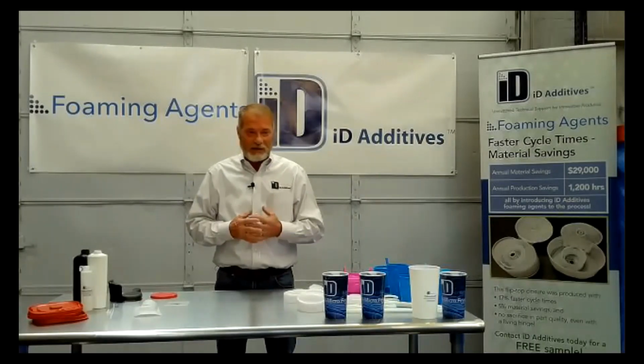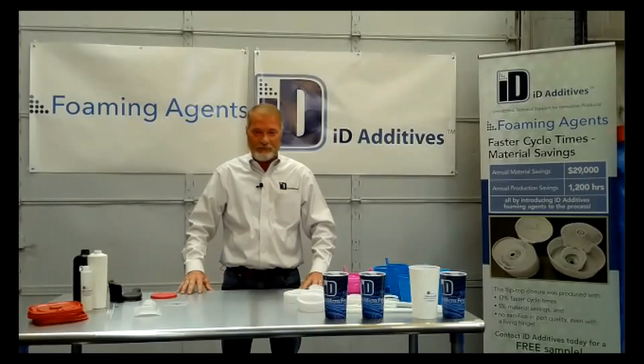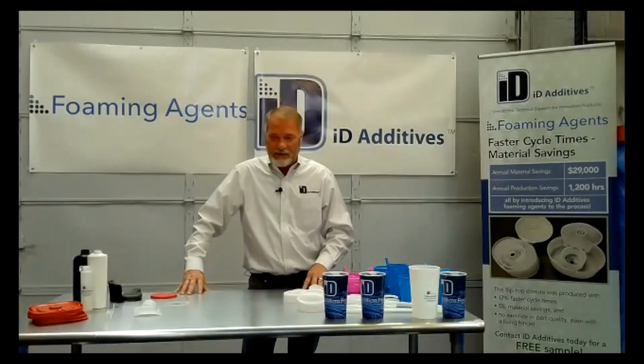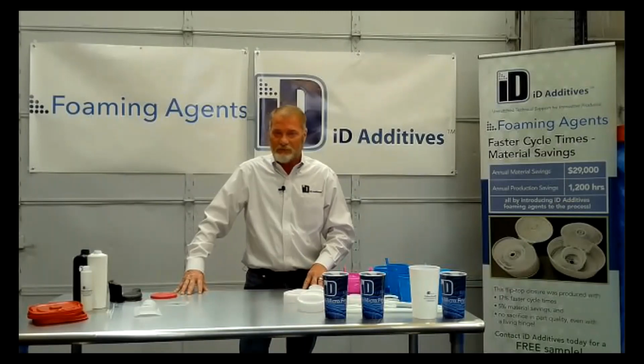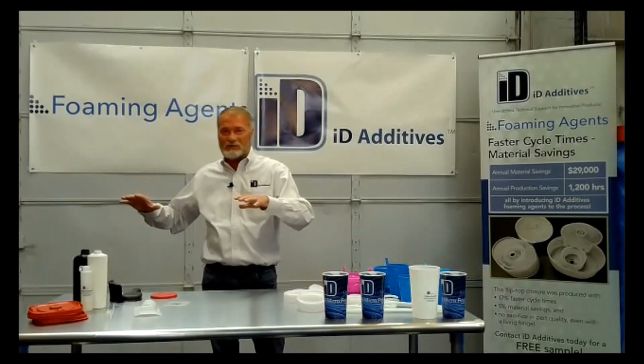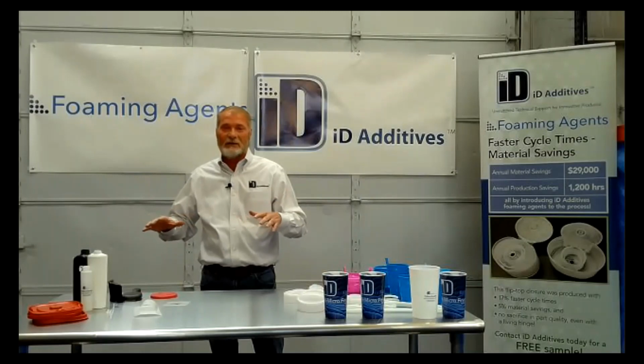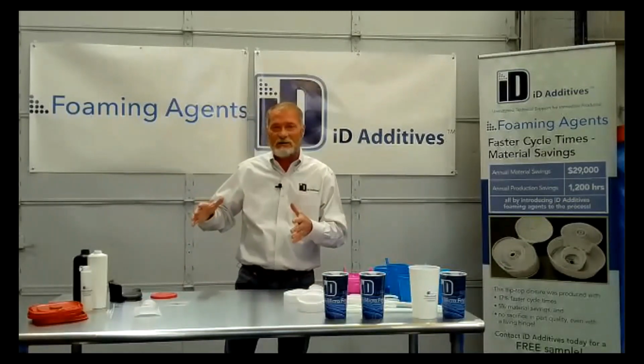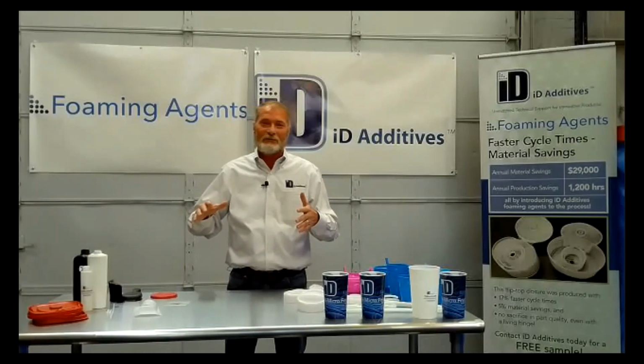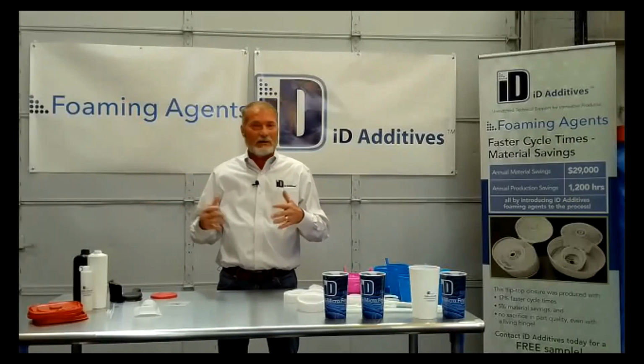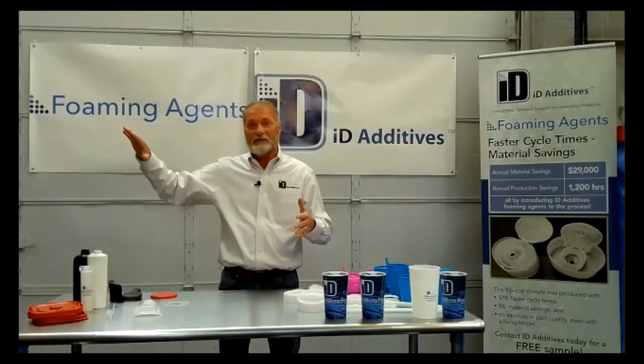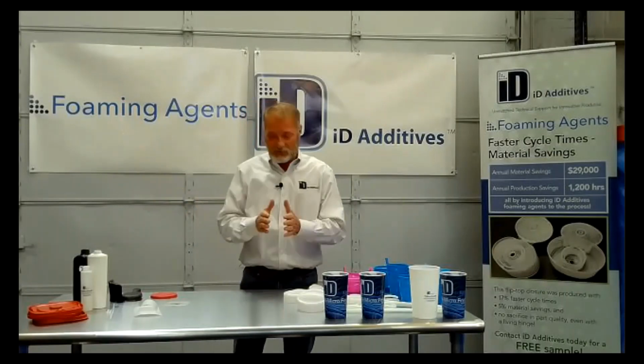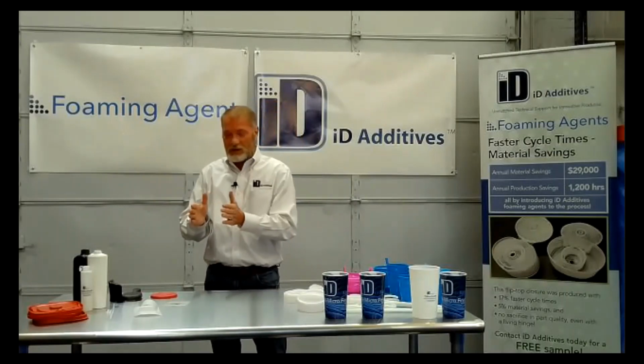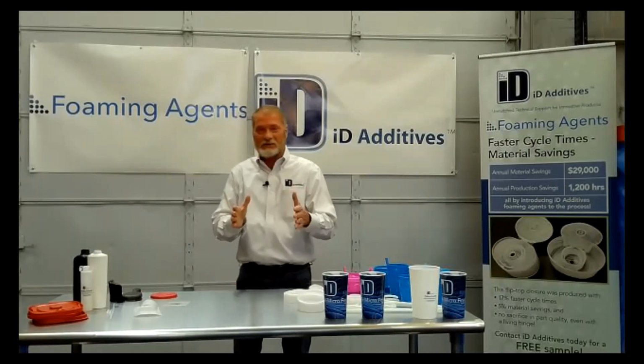I had an application just recently that was polycarb, and they were running it and they weren't seeing any gas at all in the part. They lowered the rear zones, they kept everything really tight. Problem was there were too many shots in the barrel, so the gas was going up the hopper. They were getting a little bit, but not nearly enough. So basically what we did was we moved the shot size up, moved the transfer up to where you had a good size cushion.